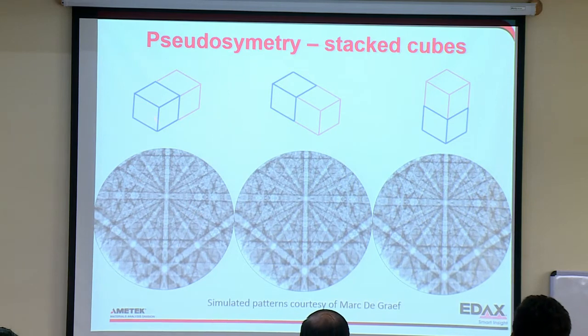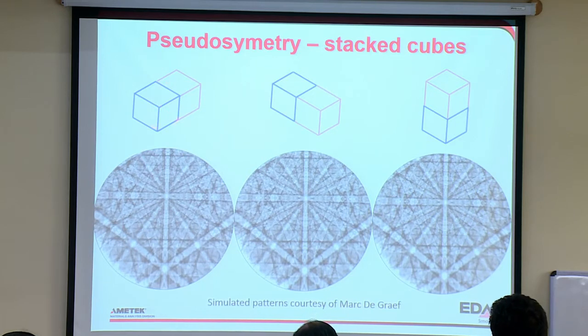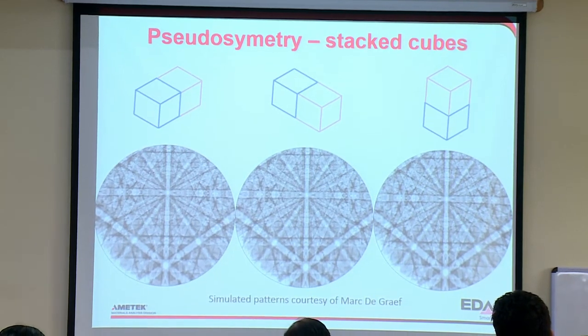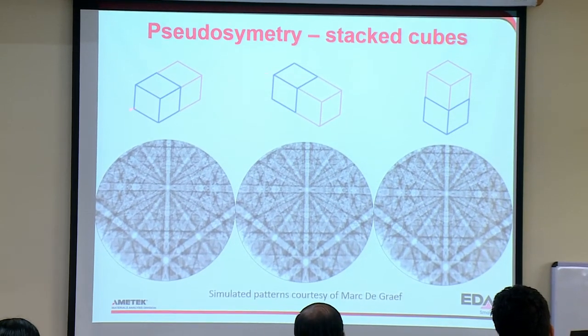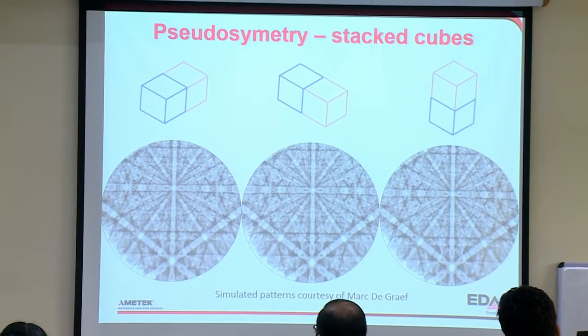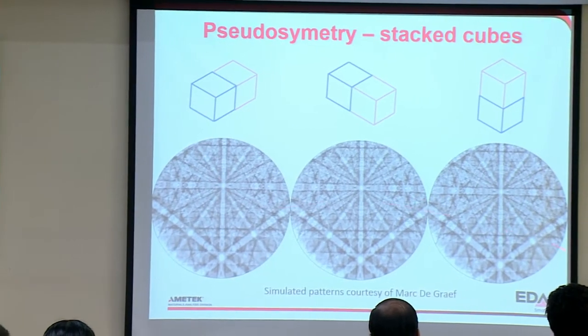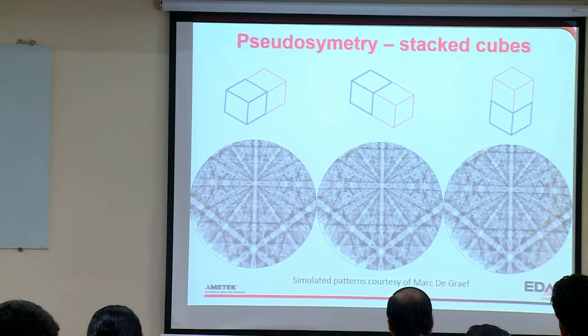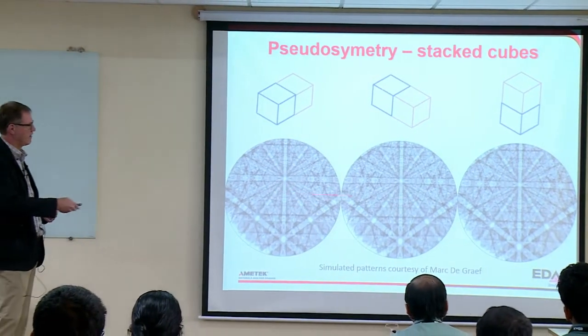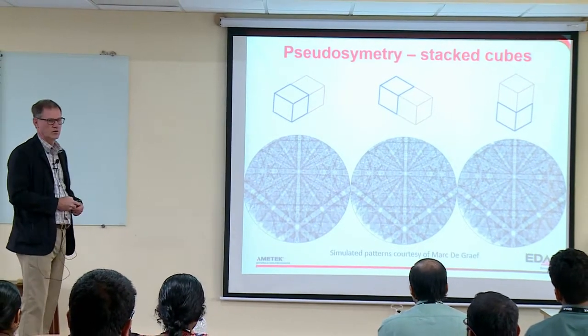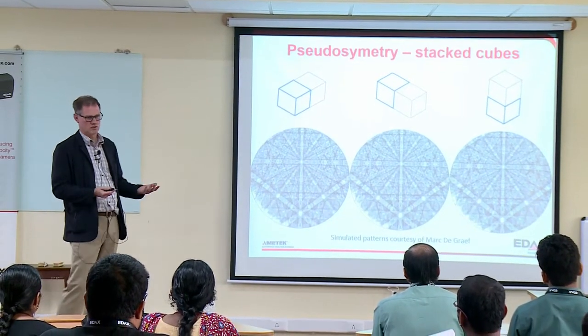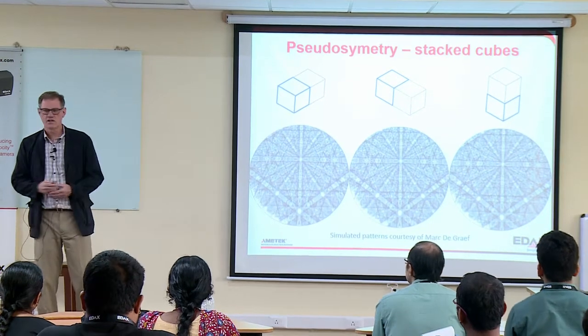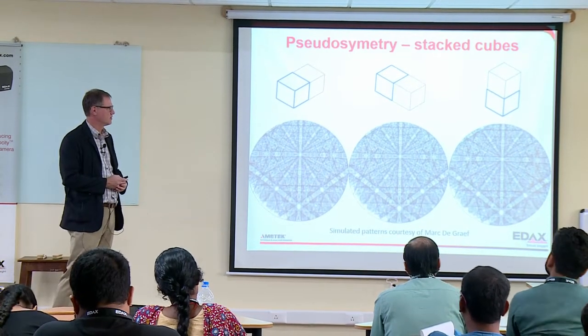So what I have here, you can see the cube in three different orientations. But if you look at the blue cube, it's actually in the same orientation in all three cases, even though the overall structure is in the three differentiable orientations. And if you look at the patterns, they're almost identical. And so you can see EBSD would have a hard time differentiating these three orientations. And we call this pseudosymmetry. And it's a problem that we see, one of the challenges of EBSD in certain materials.